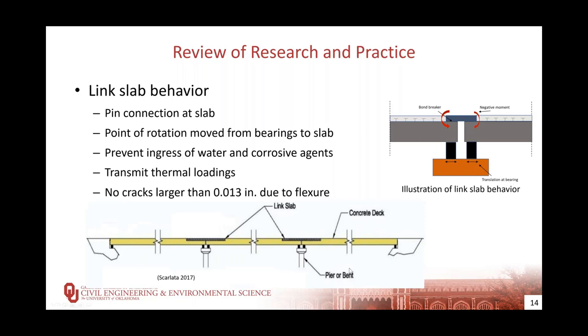The link slabs are still able to transmit the thermal loadings axially along the length of the bridge. And we're looking to limit the crack widths, just like what we try to limit for anything else, to less than 0.013 inches due to flexure. We have a couple of illustrations here showing that we still get translative movement in the direction of the bridge, but rotation at the link slab. And again, we can eliminate some of those joints and place link slabs over the piers.